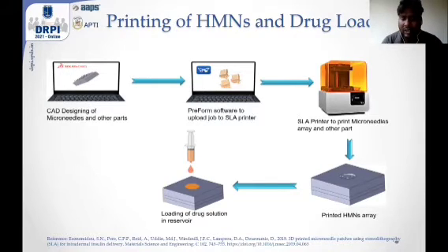The job was uploaded to the SLA printer, where the SLA printer Formlabs Form2 was used for the printing of the hollow microneedles. After printing the hollow microneedles array, it was washed using 99.9% isopropyl alcohol to remove the adhered resins, and then the drug solution of rifampicin in ethanol was loaded.